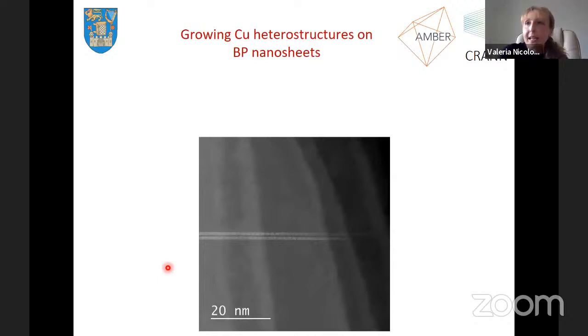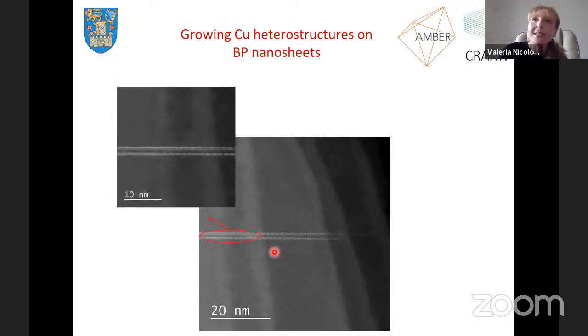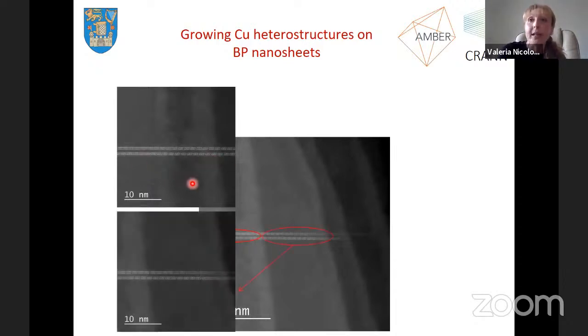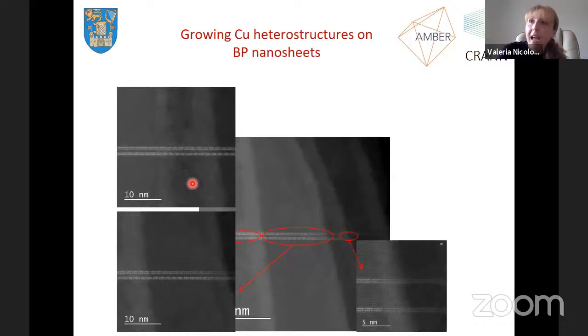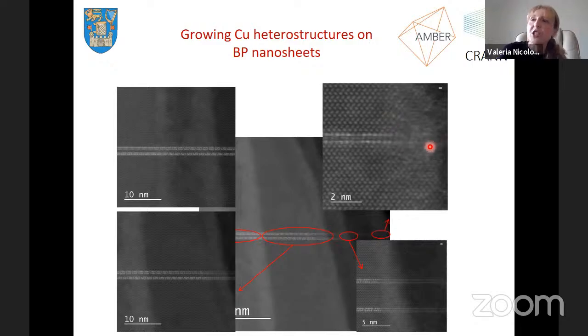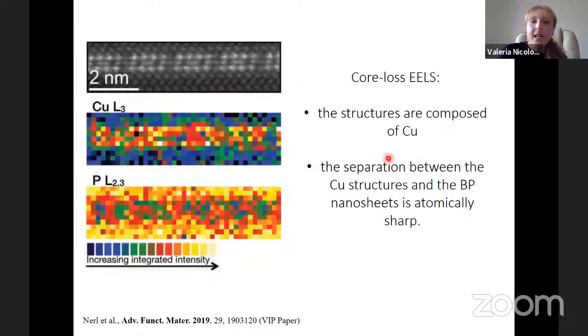So we looked at it in the aberration-corrected STEM. We looked at these lines, and for our great surprise, these lines had an amazingly well-ordered structure. So you can see how ordered this structure is and how periodic it is. It was quite a discovery. And it goes straight up till the end of the layers where the edge is, and then it finishes with the edge. It was impressive to see how structured it was. We understood by doing EDS that indeed these lines were made of copper.